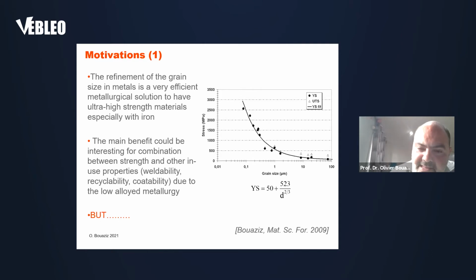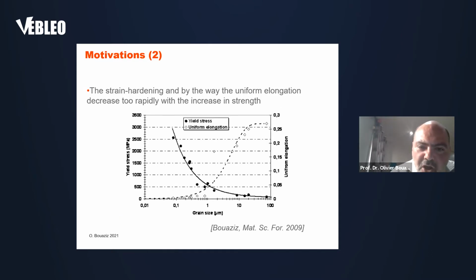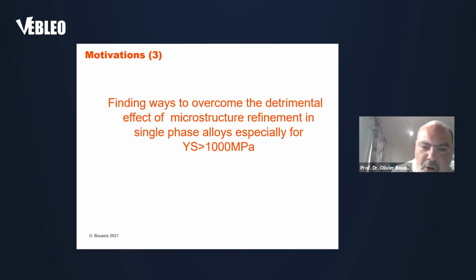But there is a problem, because the YS increases a lot, but the uniform elongation, so the strain hardening, drops dramatically to a low level, and it is a strong limitation for the use of this kind of material. So the problem is we have to find ways to overcome the detrimental effect of microstructural refinement in single-phase alloys, especially for YS higher than 1 GPa.